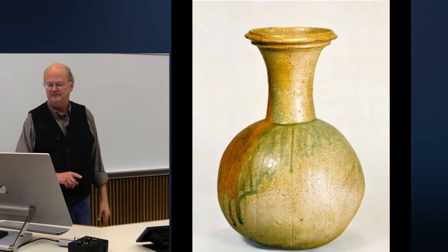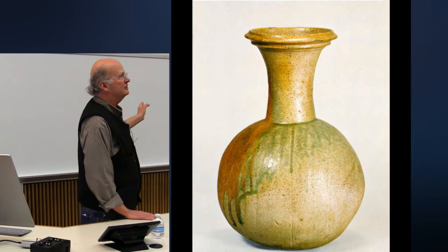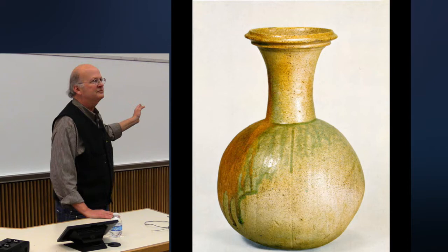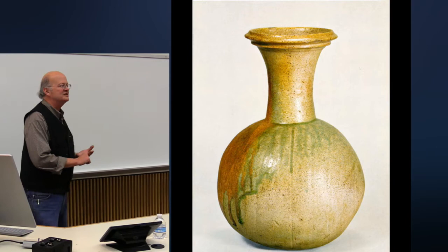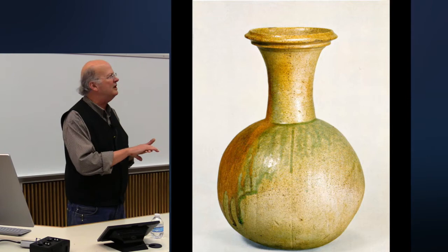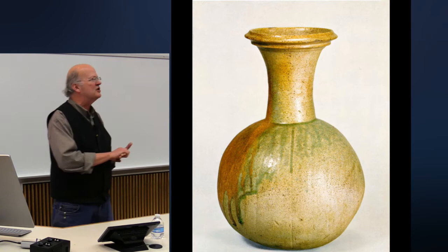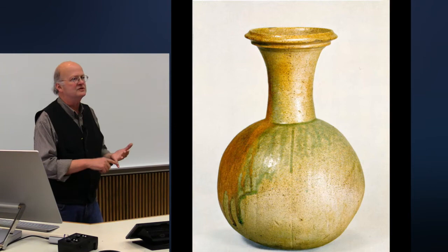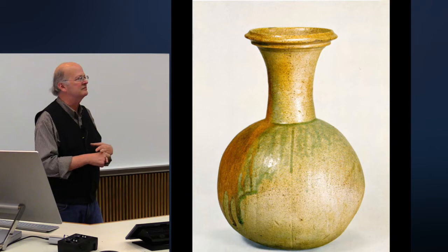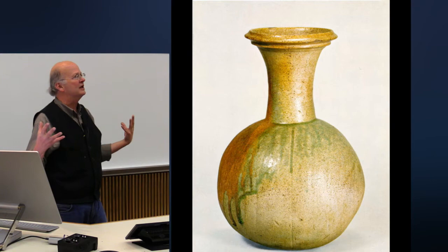Some of them got quite thoroughly covered with that fine glazed-like surface. I should point out, too, that in the process of combustion, not only is there wood ash that results from combustion, but there's also a certain amount of alkaline vapor. That is, the sodium and the potassium go through the kiln not as particulate matter, but rather as a vapor. That also reacts very readily with the alumina and the silica in the clay to form glass.